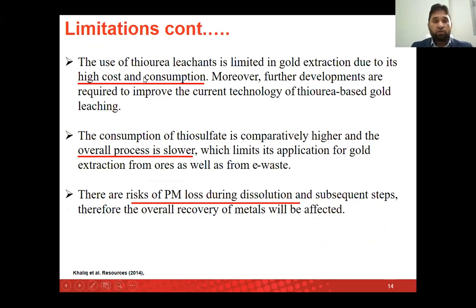Also, there is the high cost of consumption of the leachants, so that is only used for concentrated gold ores, not for low grade, because electronic waste comes under low grade, since the amount of gold and silver is not that high compared to concentrated gold ore. Then we have thiosulfate. The process is much slower, and again precious metal is lost during the dissolution. So to summarize, the hydrometallurgical routes could be good for very small scale processing, but you need to be careful what kind of leachant you are using. Also there is a significant loss of the precious metal along the route.